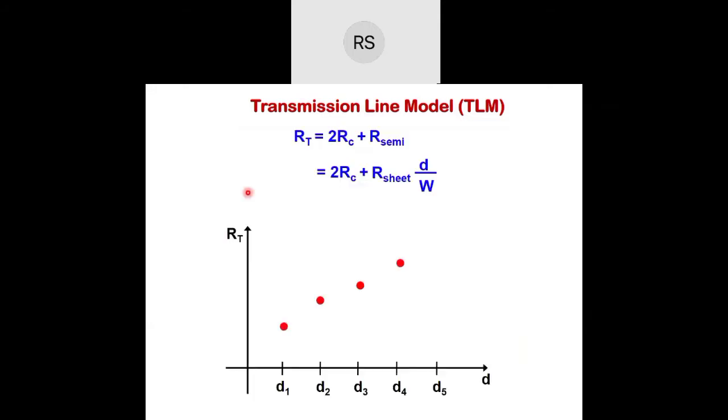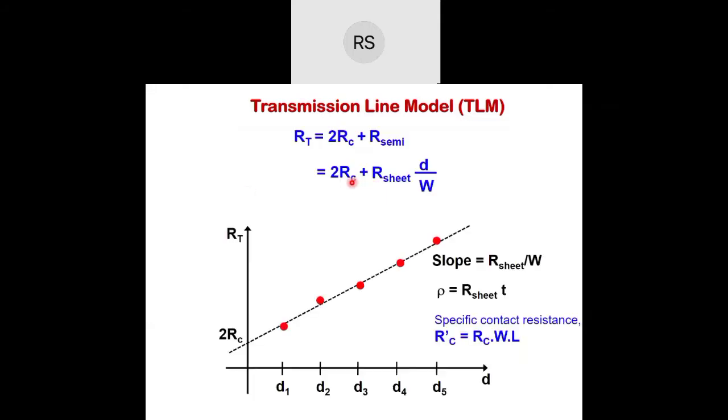By fitting this line, I get the value of R sheet by W. W I already know, so I can calculate the value of R sheet.